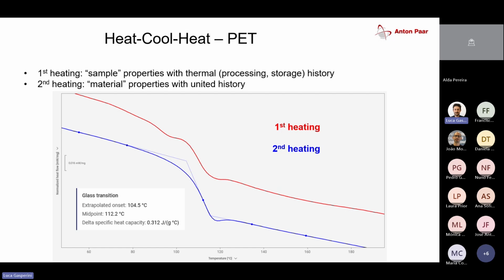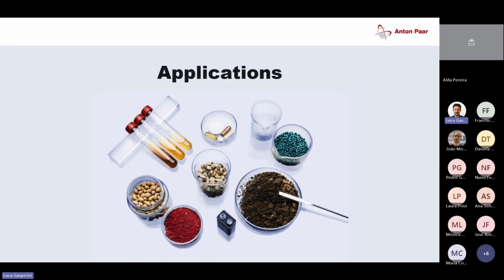So this is an example of PET again. During the first heating, we see the glass transition at around 100 degrees. We see there's a tiny little endotherm here, and then something broader here, which might be effects related to the relaxation of the sample, because during the manufacturing, we gave the sample some properties. But then if we heated the sample up, cooled it down and heated it again, we see a textbook example of a glass transition with a tiny little bit of enthalpy relaxation. But it's a much nicer step, which can be analyzed in an easier way, and we don't actually see these effects anymore. So cool-heat is a very common thing in a DSC, especially when it comes to looking at thermal history. And now I have a couple of application examples.